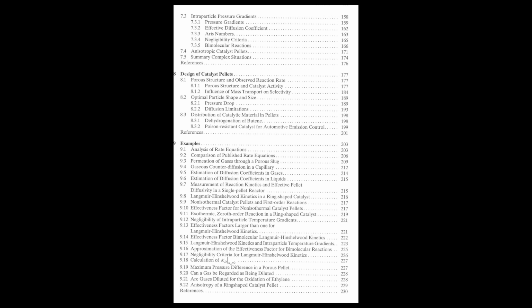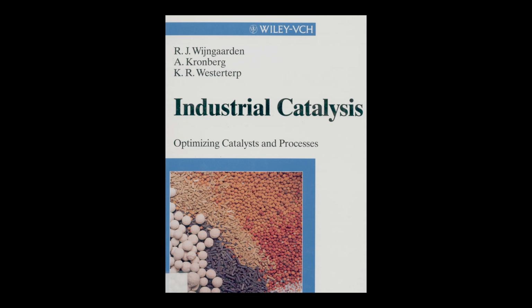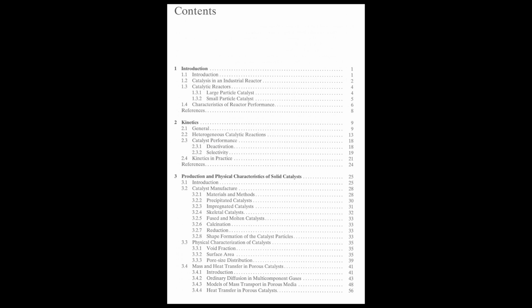One is fouling, where deposits like coke, which is basically a carbon-rich gunk, build up on the catalyst surface and physically block the active sites. Reactants just can't get to them. Like clogging pipes. Exactly. The other is poisoning. This happens when certain compounds present in the feed stream, even in tiny amounts like maybe sulfur compounds, strongly adsorb onto the active sites. They essentially stick there permanently, blocking them off and making them unavailable for the desired reaction. So the catalyst gets clogged up or its working parts get jammed by impurities.